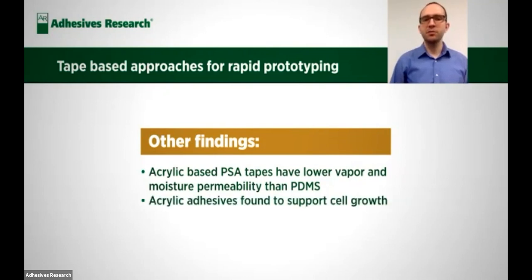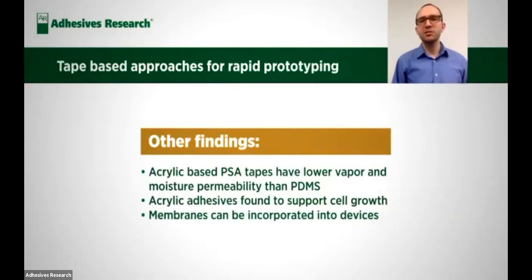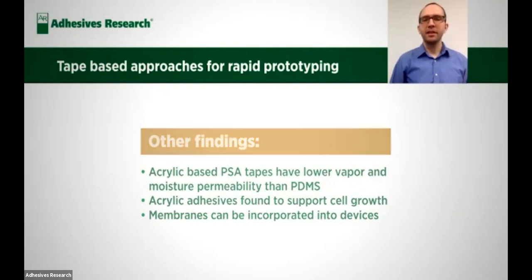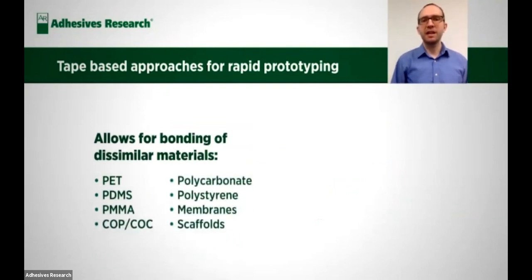Acrylic adhesives were also found to support cell growth on their own, which is a problem for other types of materials used in microfluidic devices. And then the membranes and scaffolds can be introduced into the device on their own through the use of the PSA tapes, which allows for the support of organ cells and other types of cell growth. I think another major advantage of this type of approach is it allows for the bonding of dissimilar materials. So PET, PDMS, PMMA, COP or COC, polycarbonate, polystyrene, can all be bonded using pressure-sensitive adhesive tapes, as well as the membranes and scaffolds, as I mentioned. And that can provide a huge advantage.